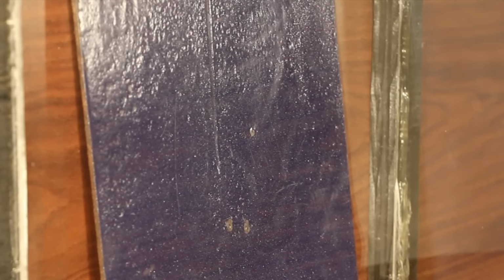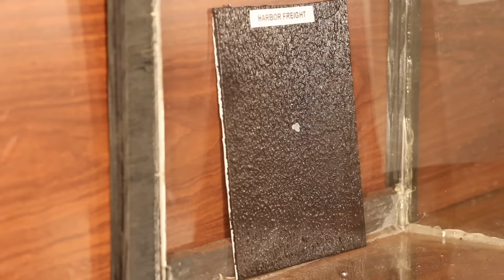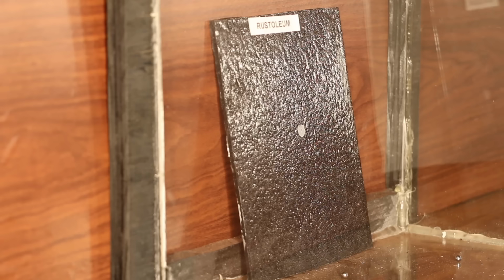The amount of damage to the painted steel plate was a little bit less at ambient temperature at 4.58 millimeters. The amount of damage to the Harbor Freight Iron Armor was slightly more than at sub-freezing temperatures at 9.42 millimeters. The warmer temperature really helped Rust-Oleum quite a bit with the damaged area at only 6.35 millimeters.